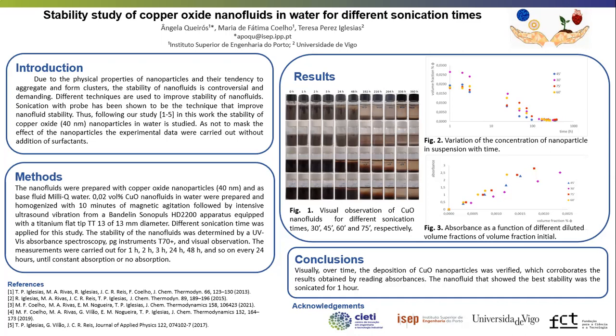0.02% CuO nanofluids in water were prepared and homogenized with 10 minutes of magnetic agitation at 500 RPM, followed by intensive ultrasound vibration from a Bandelin Sonopuls apparatus equipped with a titanium flat tip TT13 of 13 mm diameter. Different sonication times were applied at 10% of maximum power. To prevent overheating, the sample-containing flask was immersed in an ice bath.